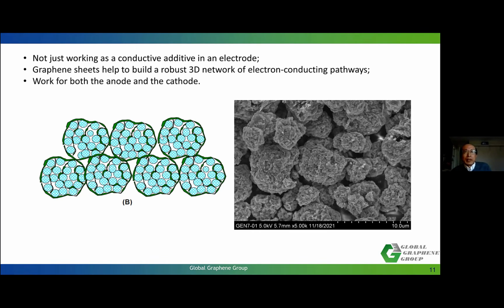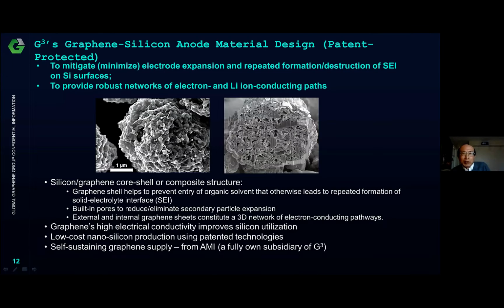This is an SEM picture of our product. As you can see, we have very thin, visible graphene sheets on the outside, encapsulating the silicon particles along with other ingredients inside these secondary particles. We use a focused ion beam to cut the cross section, and then we can see the internal structures here. Our silicon-graphene composite structure has the following features. Our graphene shell can help prevent the entry of organic solvent that would otherwise lead to repeated formation and destruction of the SEI layer, which continues to consume lithium ions. We also have built-in holes or porosity to reduce or eliminate the secondary particle expansion.